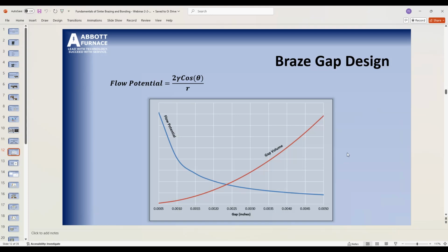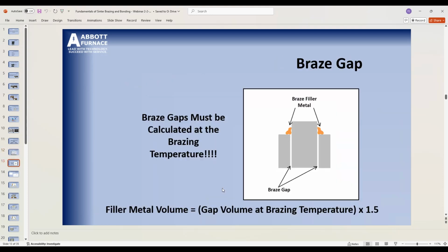I've seen people design around a 5 thousandths gap and get away with it, if you have the time and everything's perfect. But once you get above that, they start to have short shots. They can't pull the filler metal through the gap, and so they don't get a good braze. Or if the gap is too tight, there isn't as much filler metal to actually form the bond. So my optimal is about 2 thousandths.